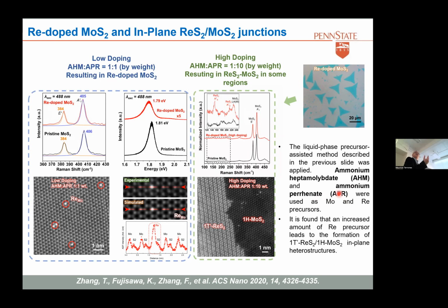So basically, you mix these two, and you can mix them with different ratios by weight, and then you end up having either rhenium atoms in the lattice here, or you can have a rhenium disulfide interface of 1T prime rhenium disulfide and the 1H or 2H molysulfide here. Depending on how much rhenium you put, you can have more doping, or you can have these sharp edges with the rhenium and the moly. And then you have this growth of these triangular systems.